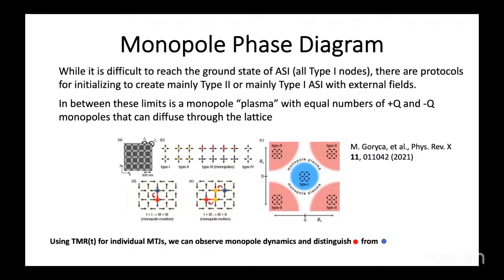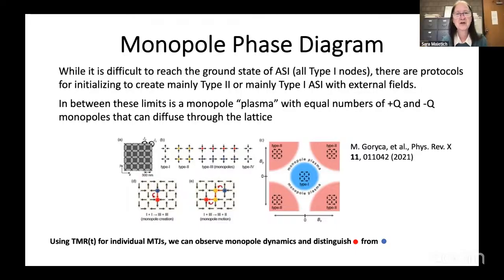Exactly. And the most important point is that you have very long relaxation times for this system. We're really just at the beginning of understanding how to create that, because we were so surprised with the canting and also with the rotational boat. So when you go from simple islands to something where there's a very, very small symmetry breaking field, it was only 8 Oersteds here, but it was enough to have a huge impact on the dynamics. And since most devices that would be electrically controlled would have a structure kind of similar to what we've got, we really want to understand this.